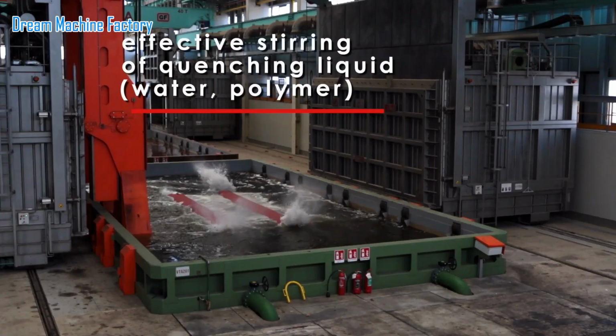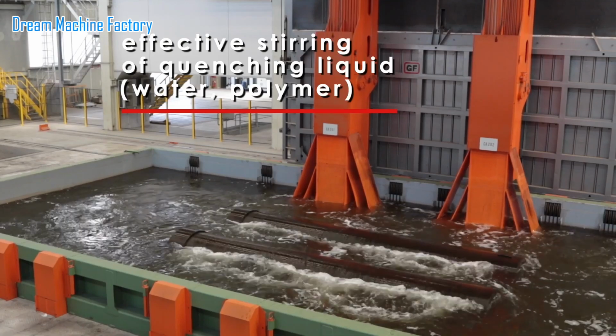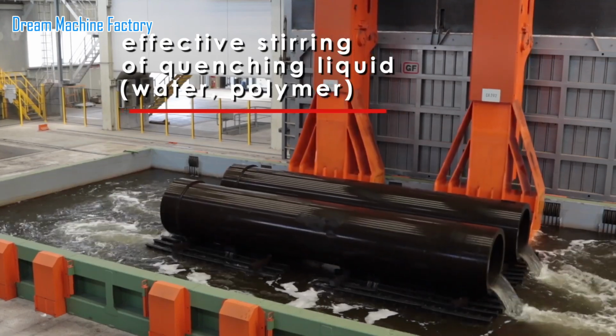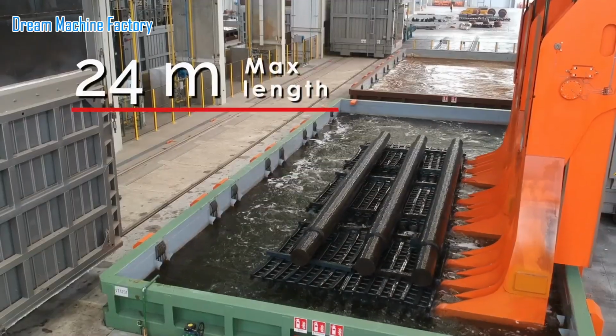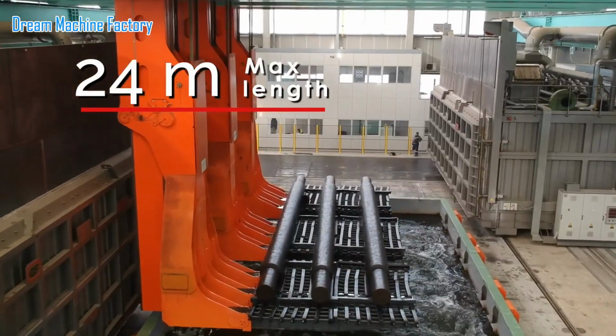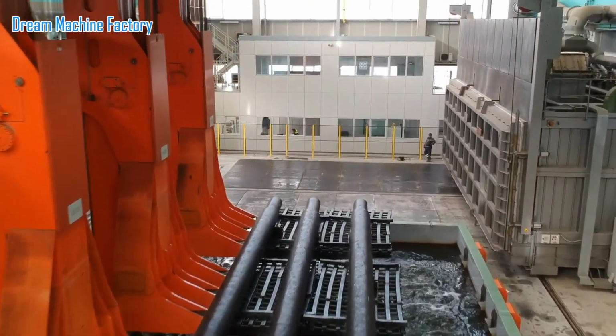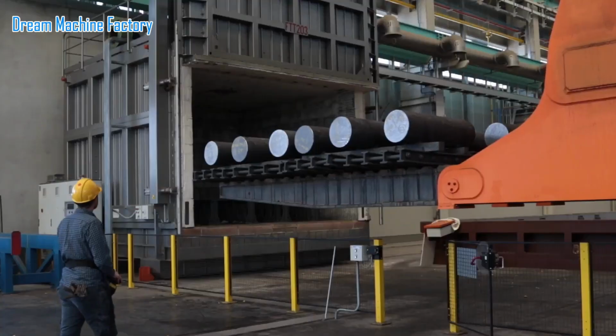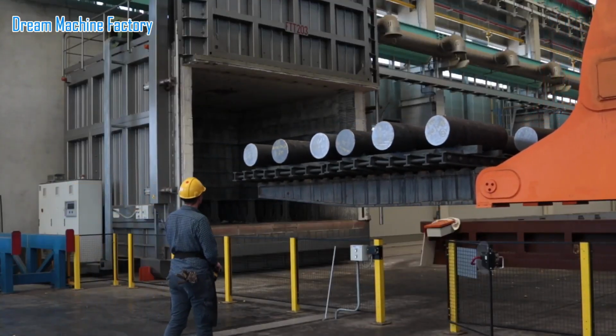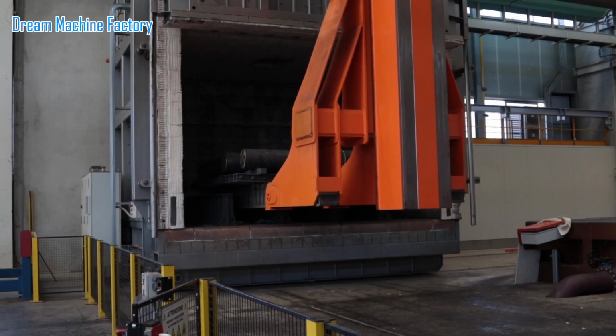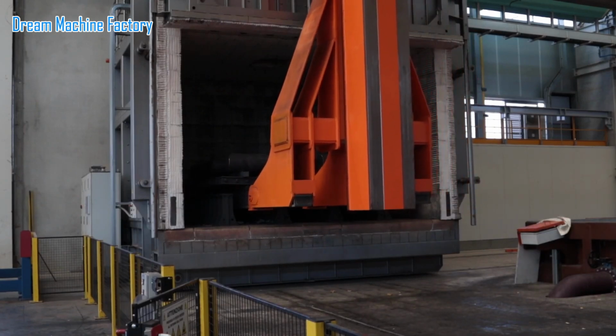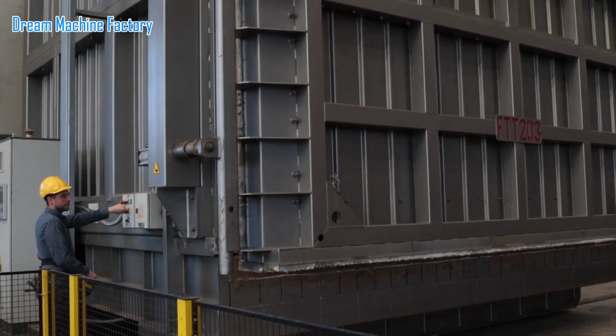The quenching tanks at Franchini Acciai are engineered for effective stirring of the quenching liquid, either water or polymer, using adjustable speed propellers. This controlled agitation ensures uniform cooling, critical for achieving consistent mechanical properties. The system accommodates forged parts up to 24 meters in length, enabling treatment of exceptionally large components.